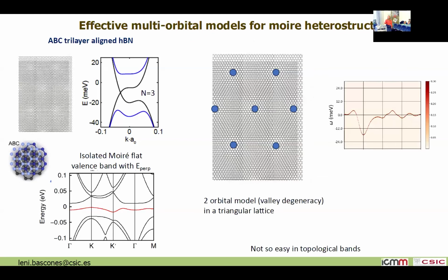Okay. So for example, imagine this is ABC trilayer graphene, which is aligned with boron nitride. We saw this has these flat bands, and it folds with the boron nitride. Before, some people asked how large this displacement field has to be to isolate the bands. Later we can check the experimental displacement; in terms of the voltage drop it is normally of the order of 20, 30 milli-electron volts. But later we can check in one of the pictures how large is the D that you put.